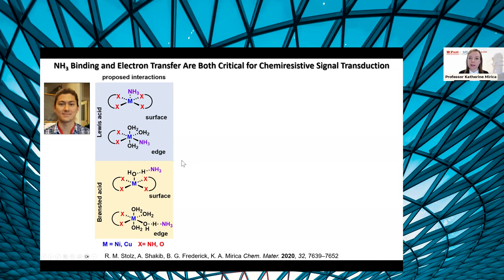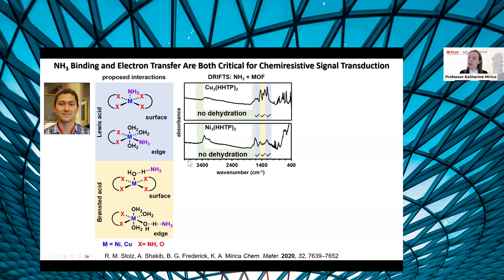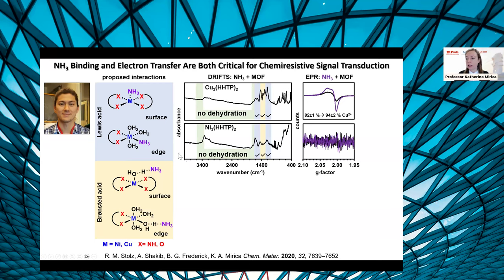So using diffuse reflectance infrared spectroscopy, as well as other techniques such as electron paramagnetic resonance, what we conclude about the nature of interactions of these hexahydroxytriphenylene-based framework materials is that there's a presence of both Bronsted acid sites and Lewis acid sites, but that in the case of these hydroxy-linked systems, the Bronsted acid sites can be significant, and there's no dehydration of these materials that is observed upon binding, so no water release during binding for these particular materials.